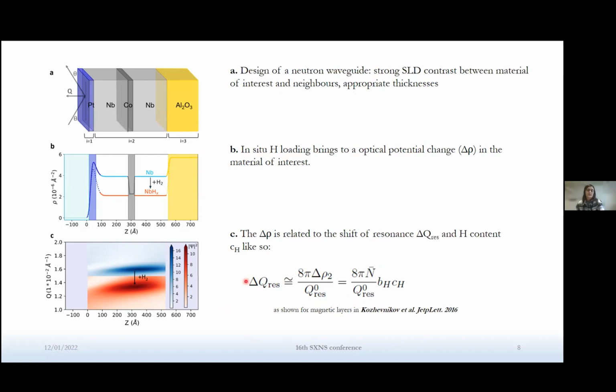And this is pretty powerful because by following this resonance, this means that we can directly know the hydrogen content in the film. Just one comment, this formula is valid only when we neglect thickness differences or inhomogeneous absorptions. So we need to take into account when we know that swelling of the film is present, and put it inside to have a proper hydrogen content.